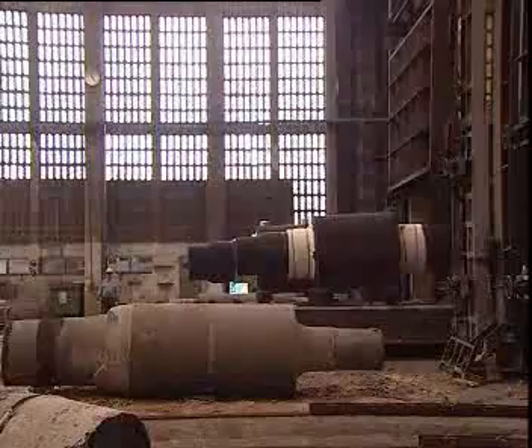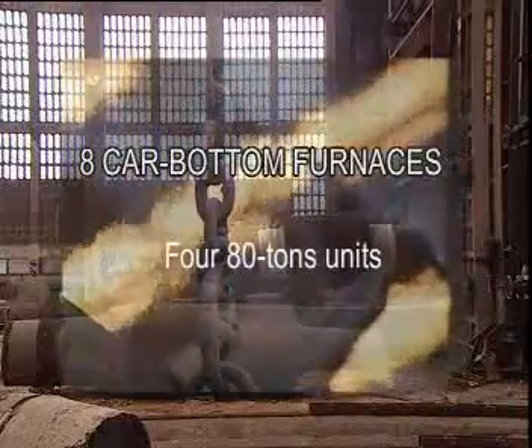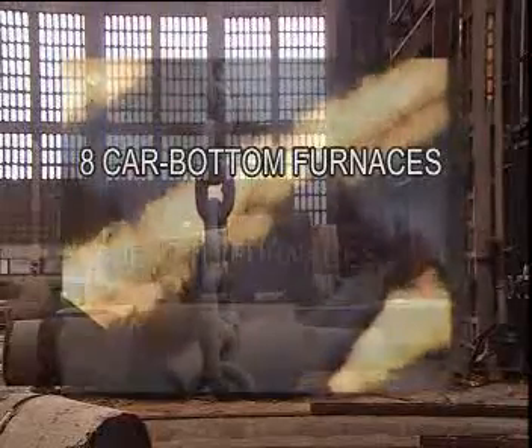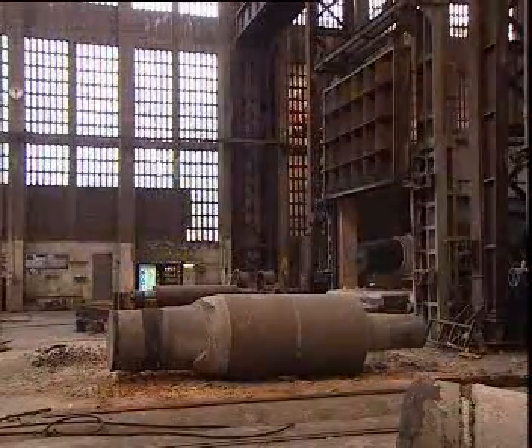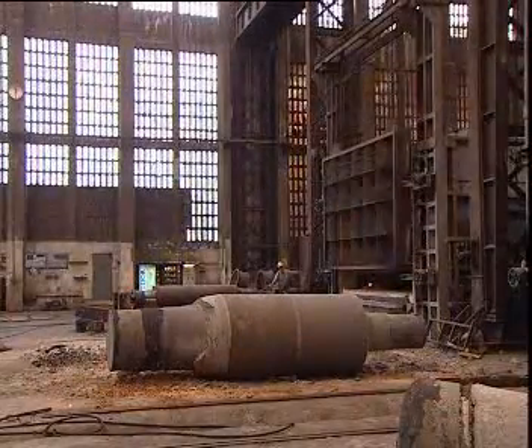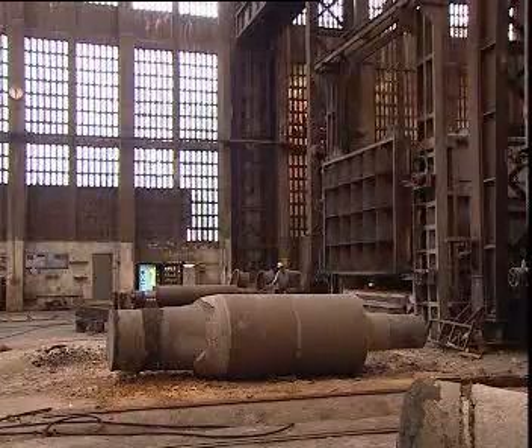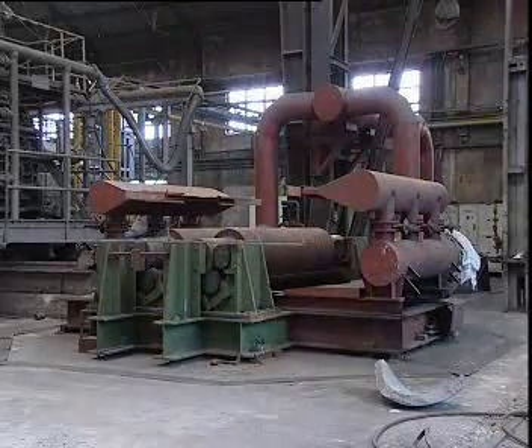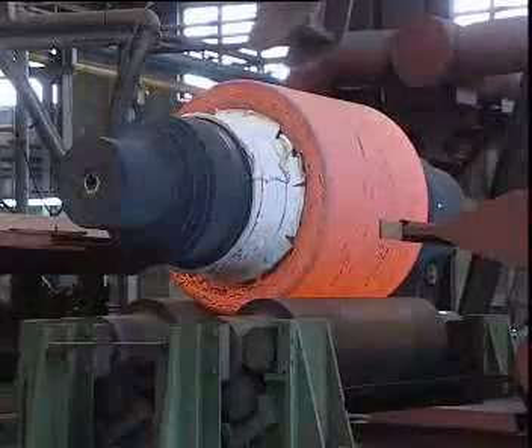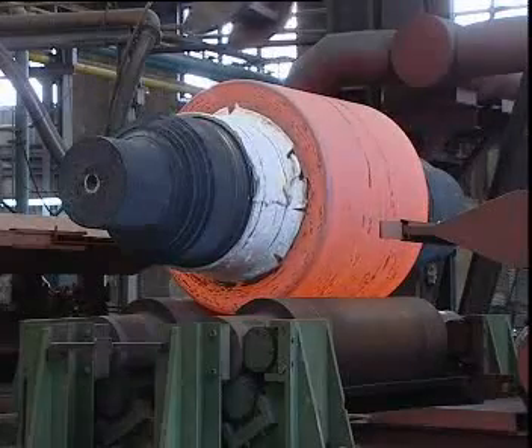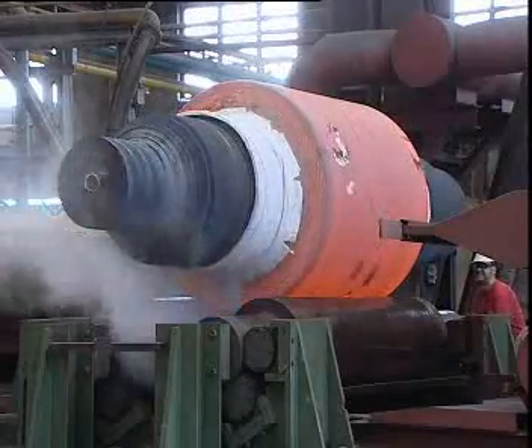We are equipped with 8 car-bottom furnaces, 4 80-ton units, 3 150-ton units, and 1 400-ton unit, as well as 2 hearth furnaces. All of them reach temperatures up to 1,100 degrees Celsius with air circulation and fully automated controls, in which annealing, tempering, and stress-relieving operations are performed. 2 high-tech air and water machines with automatic temperature gauges enable us to quench and harden any type of material.